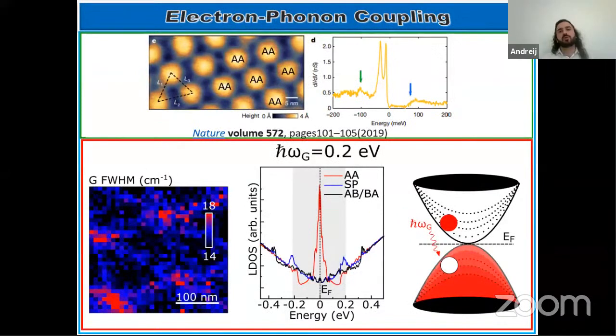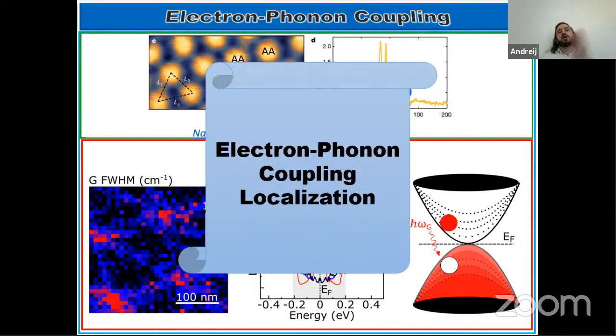And when we compare to what people observed before, this is an STM measurement, and it tells us that the electronic density of states is higher at the AA sites. And here we are showing that the electron-phonon coupling is also higher at the AA sites, okay? And in addition to that, the electron-phonon coupling also suffers from localization effects.